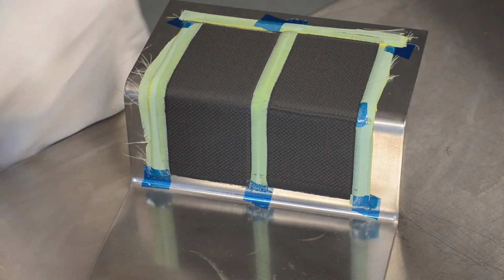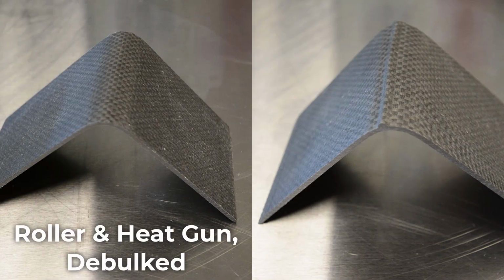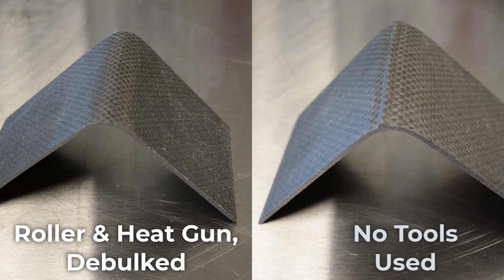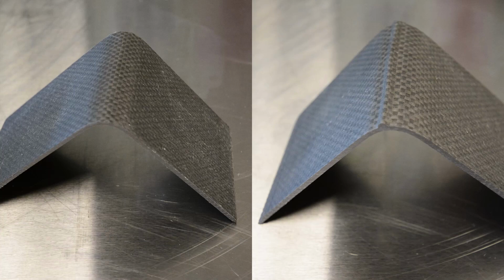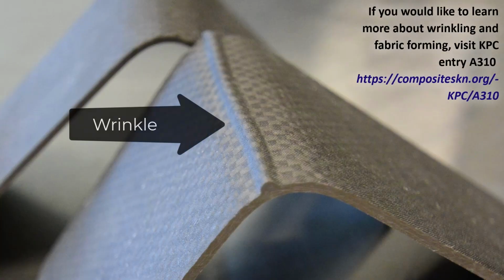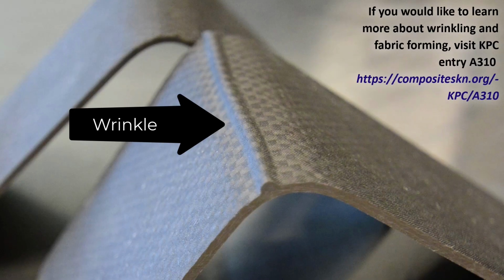After curing the two parts, it is apparent that the plies that were debulked and positioned using a roller and heat gun produced a part with fewer wrinkles and more consistent thickness. Wrinkles can reduce mechanical properties considerably due to the fibers no longer being oriented in the desired direction.